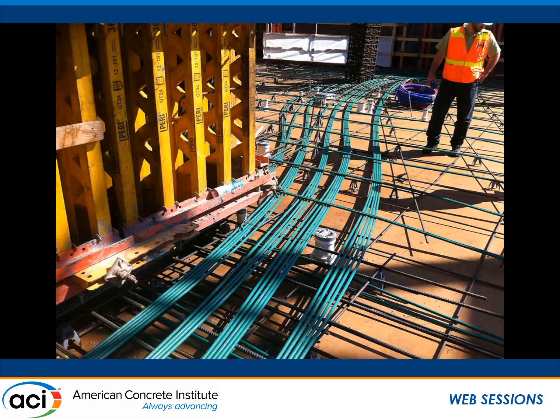This is a core wall right here, and you can see the sweep of the tendon. One very important thing with PT is when you have a massive sweep of a banded run as such, it's critically important to not only put hairpins, like some of the standard details show in the industry, but more importantly than the hairpins, to separate the cables when the sweep occurs, so you can allow concrete in between the cables. And that becomes more important when you have a high point and the cables are sweeping, so the cables only have about an inch or an inch and a half cover on top.